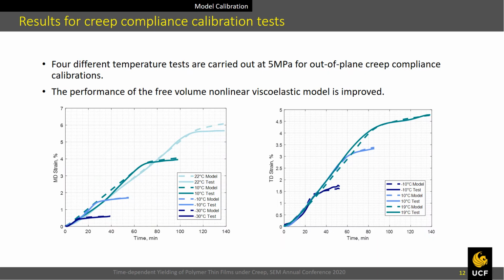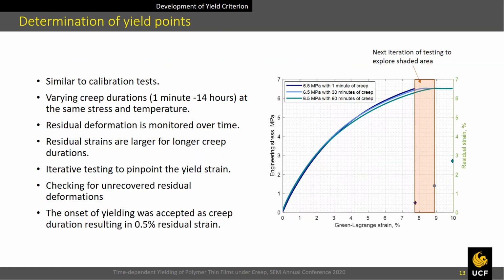The following figures display the result of model calibration by optimization of out-of-plane compliances with the experimental data. The second objective of this study requires observation of yielding at various temperature and stress levels. In this study, we would like to know when the material will yield under specified stress level. Checking for unrecovered deformations is the most suitable method for determining yield points.